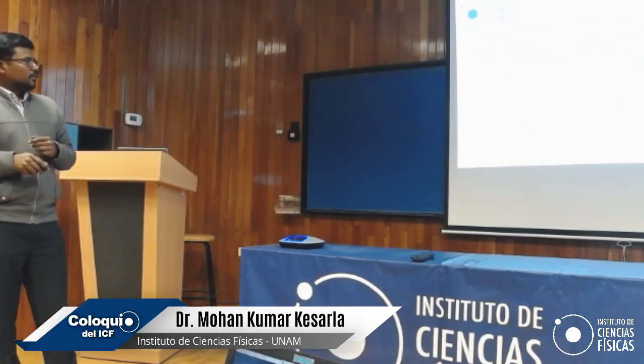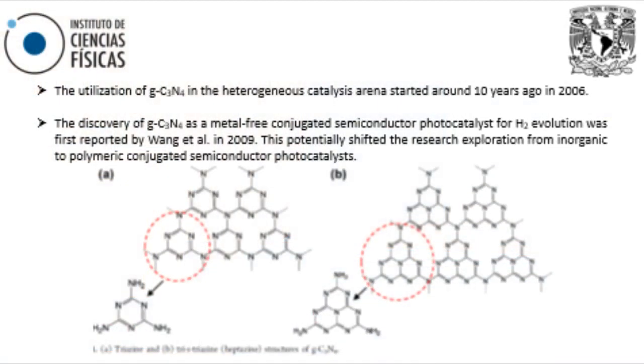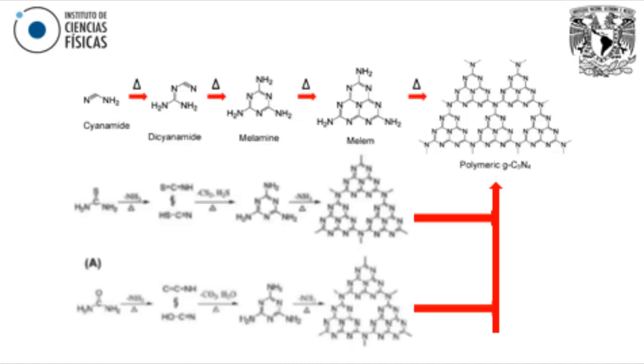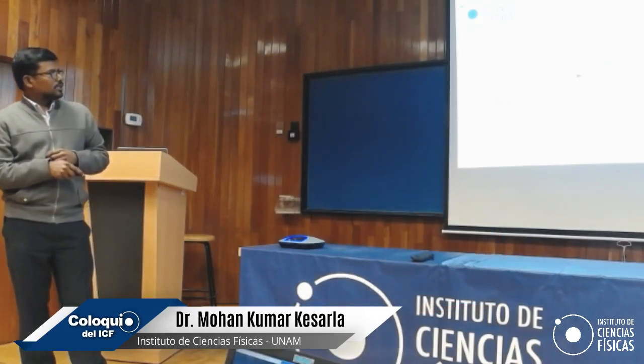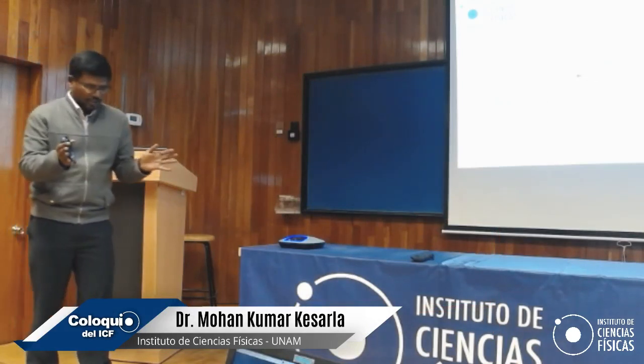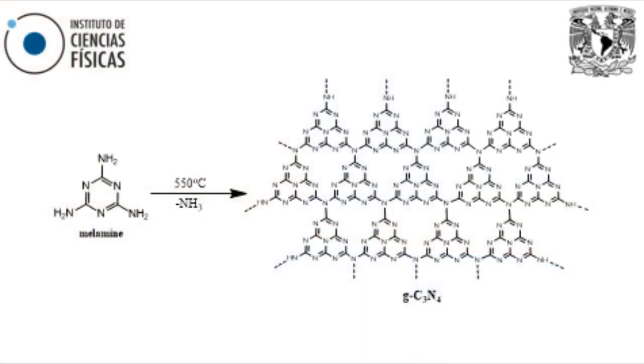So actually, we have different types of g-C3N4. The one which has tri-s-triazine units is more stable when compared to triazine systems. There are many different ways to synthesize, starting from cyanamide, thiourea, and urea. But whatever material you take, in between you encounter the same melamine. So it is very easy to do the synthetic process with melamine. You just take melamine, do thermal polymerization, and you will get the graphitic carbon nitride.